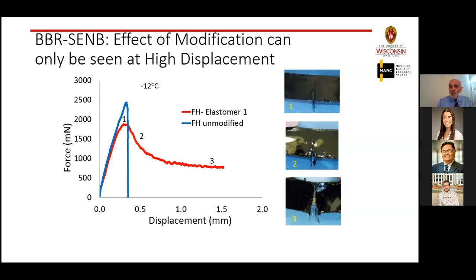You will find these two materials almost on top of each other. Many of you would agree with me. We put SBS, 2%, 3%, BBR is so minimally affected, you can even ignore that there is a polymer in it. However, if I use this cracking test, you can see the difference. As you can see here in the data collected, you can actually visually see the polymer bridging the gap in the crack when it starts propagating and giving you this very significant residual strength that can be used in the pavement significantly.